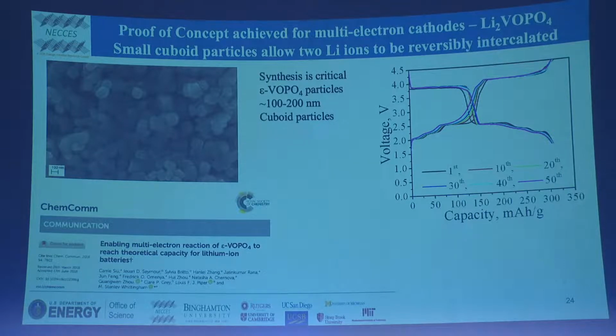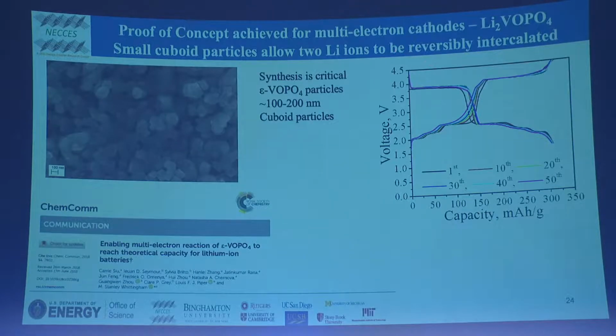So this is the material we made, little cuboids, about 100 to 200 nanometers in size. Very, very uniform. And on the right-hand side is the cycling data here. As a chemist, now, if you're going to put 2 lithiums in, you're going over 2 redox couples, so you should have 2 different voltages. So the vanadium 5 to vanadium 4 is at about 4 volts. The vanadium 4 to vanadium 3 is at 2.5 volts.